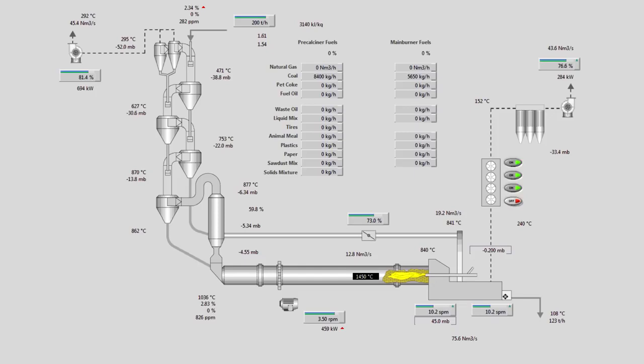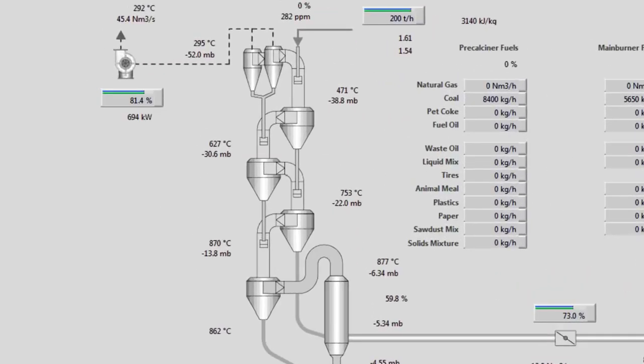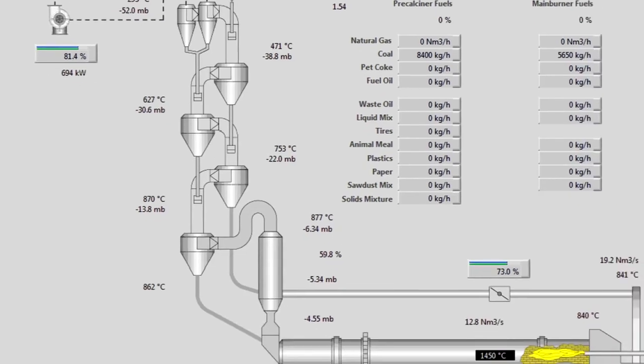To start with, I show my system running at full capacity. It is a 5 stages preheater with air-separated precalciner, 200 tons per hour feed, or 3000 tons per day clinker production. Take note of the temperature profiles on the preheater tower, the specific thermal energy consumption. Notice that we're firing coal, 60% of it on the precalciner. We have some remaining capacity in the induced draft fan.